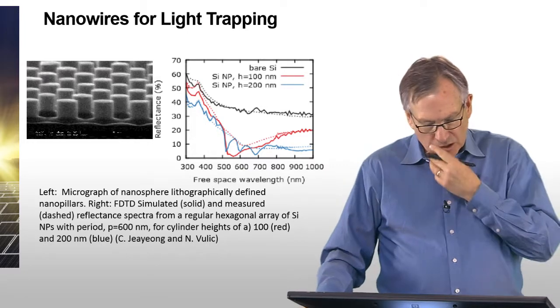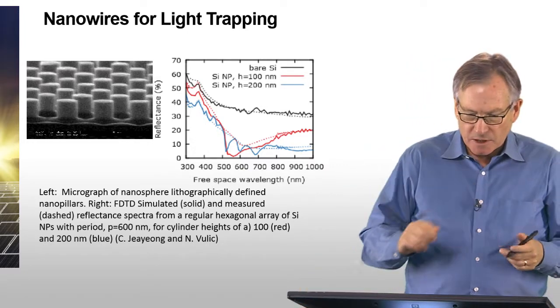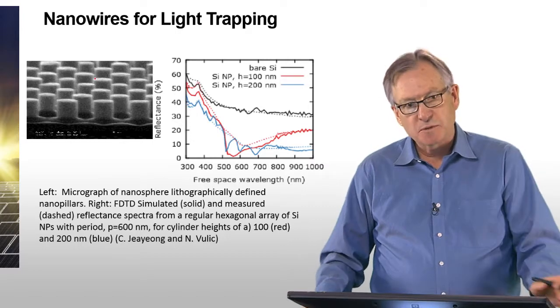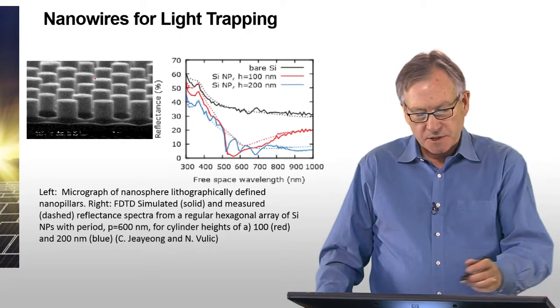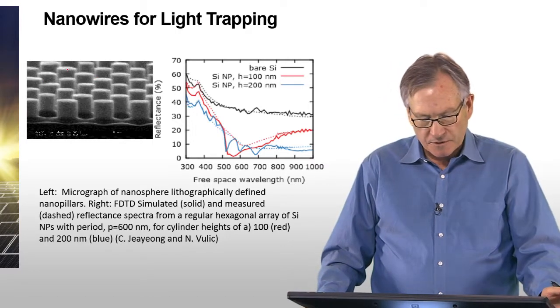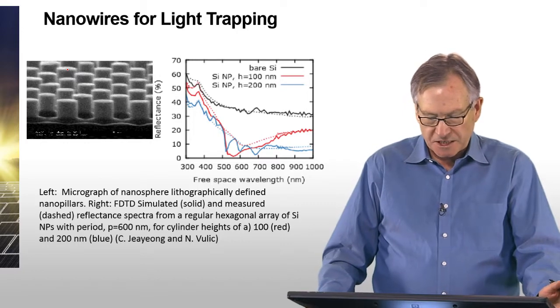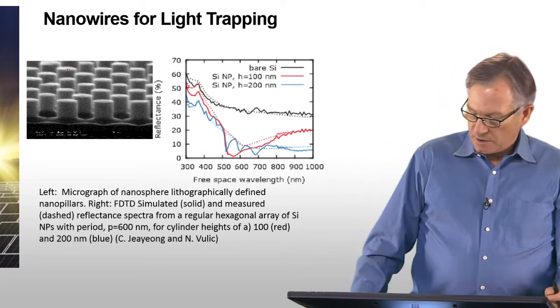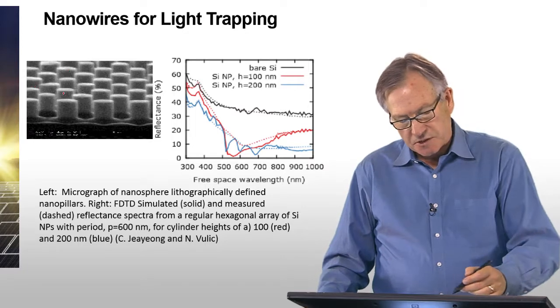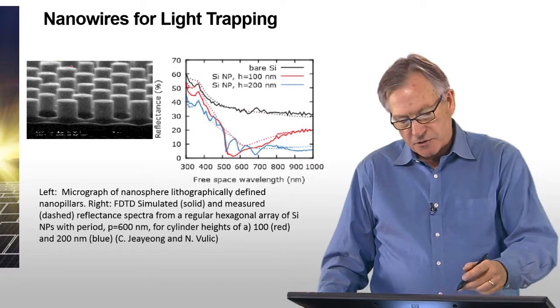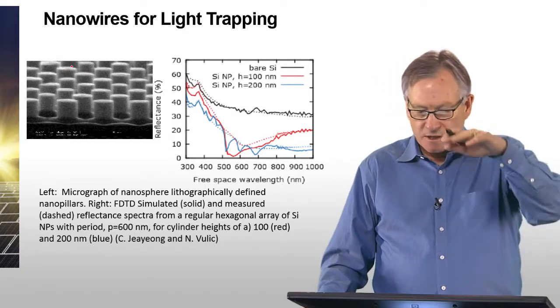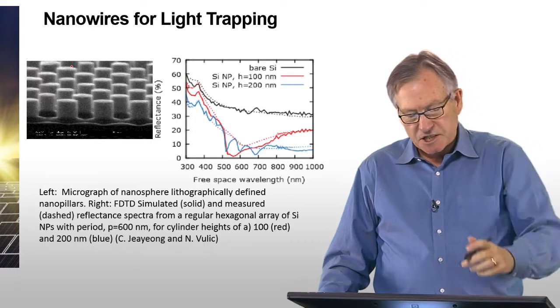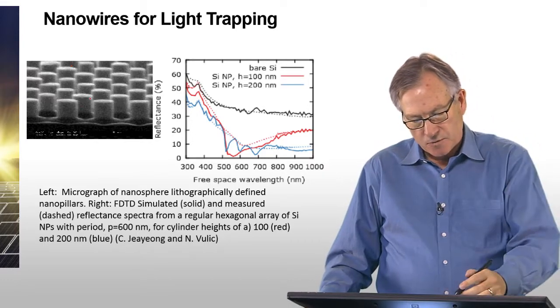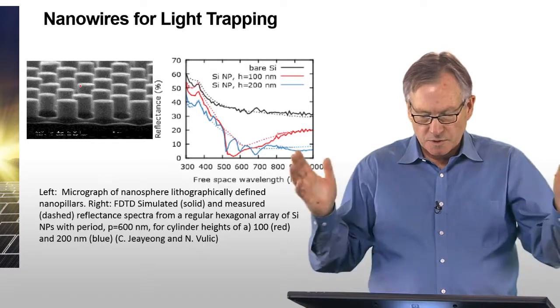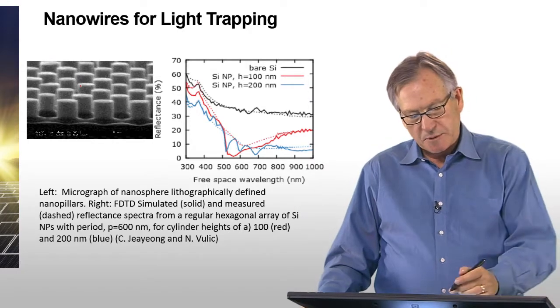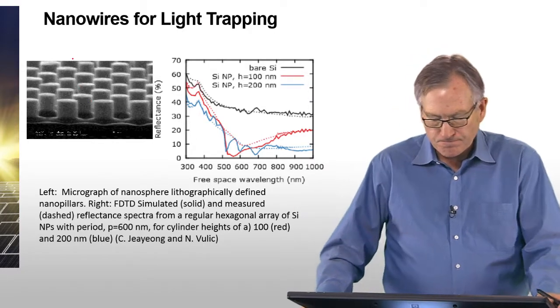This is some work ongoing at Arizona State University, and the picture on the left corresponds to a forest of a nanowire array that was formed by what's called nanosphere lithography. I don't have time to describe that, but essentially an array of nanospheres was deposited on the surface, and reactive ion etching was used to etch around those and form these pillars, and then the spheres were etched away, and you're left behind with this forest of nanopillars.